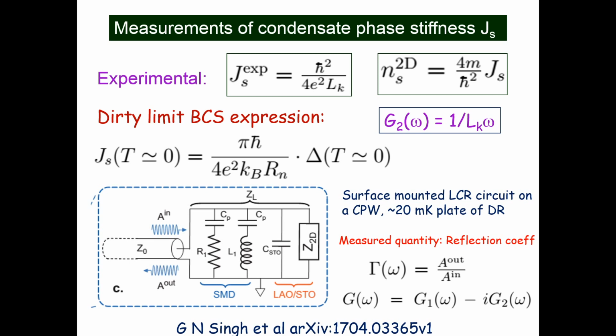And so you can see this is what we are measuring, the reflection coefficient, which is the total power out divided by power in. And this is related to the complex conductance of the circuit, which has a real part. And when the superconductivity sets in, this is my 2D layer, this is the capacitor coming because of strontium titanate, and I get an imaginary part, which is essentially coming from the response of the superfluid. And how do I write it down? This is related to the kinetic inductance of the superfluid, Lk.